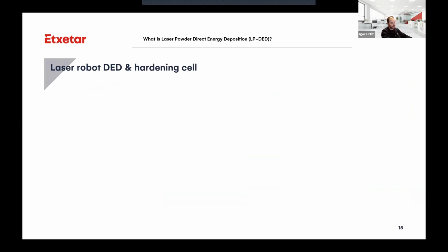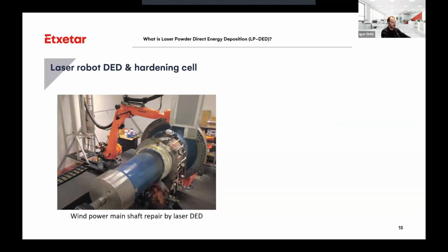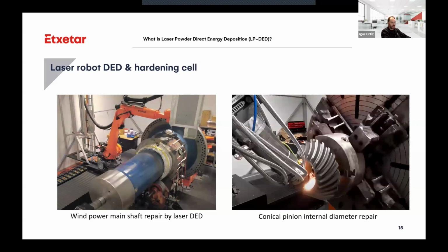So now I'm going to show two part samples that we have worked with in laser powder DED. One part is a wind power main shaft repair, where we have to preheat the 42 chromolybdenum 4 material to avoid cracks with the powder that is being cladded, in this case, Inconel 625. If there is no preheating process, the 42 chromolybdenum 4 material can develop cracks during the process. Another type of part that we have repaired, or for which we have developed the repair process with one of our customers, is the internal repair of this conical pinion. Currently, different types of shafts and conical pinions come back to service with the repair process.